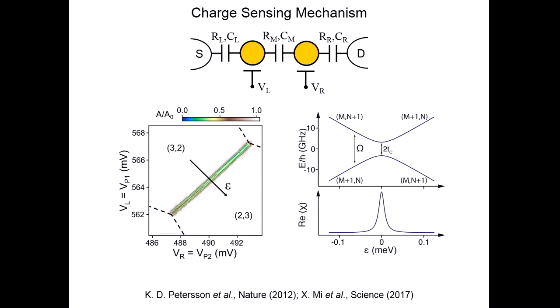But if we adjust the level detuning and bring them into resonance, then this very small microwave field can force that electron to hop back and forth from the left dot to the right dot. And there's a very large charge polarizability at that special spot where the left and right dot energy levels are degenerate. Okay? That's what gives rise to this transition. And that's why you can see that single electron hopping back and forth in these measurements so clearly. Okay? All right, let's get back to the strong coupling.